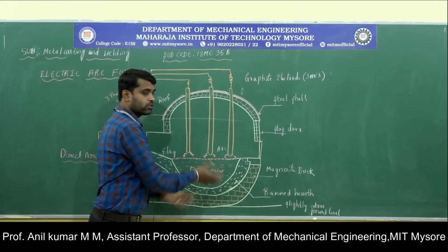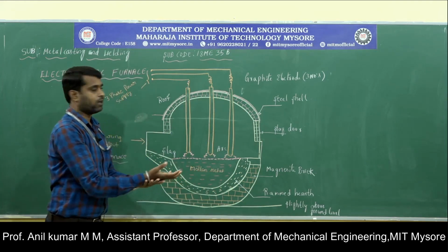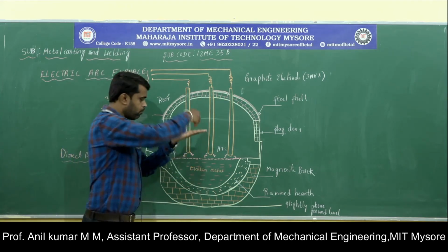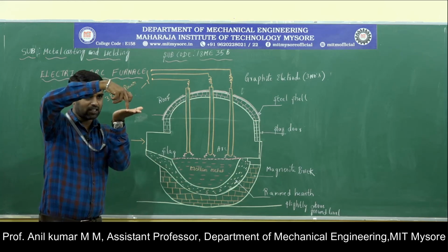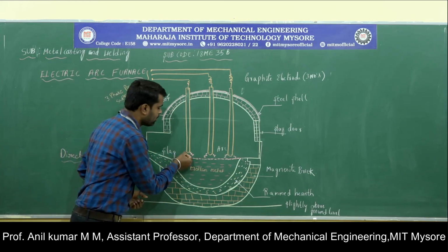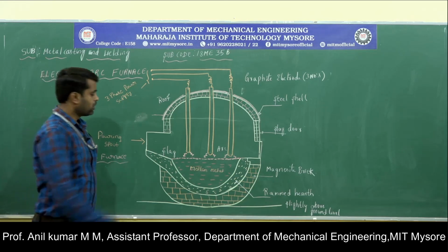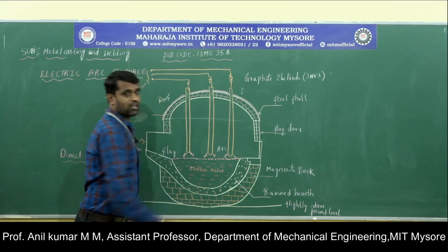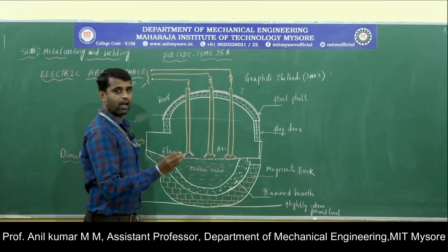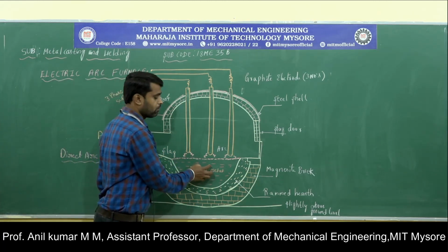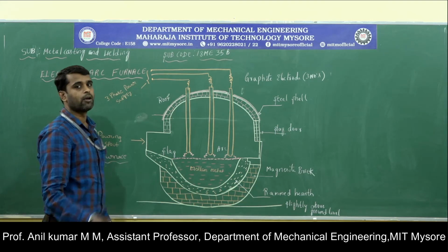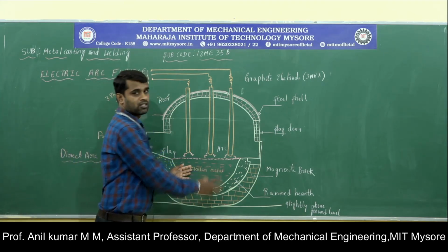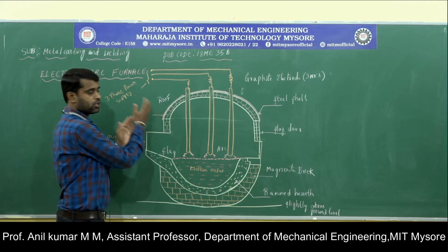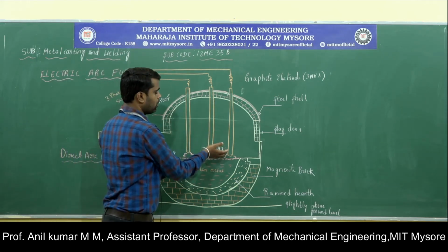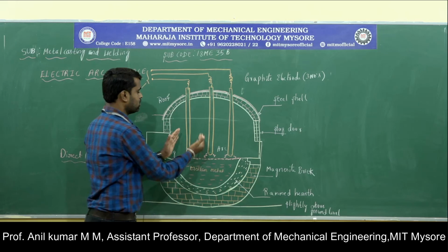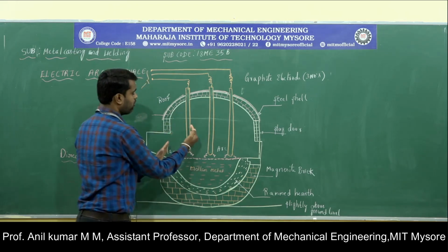Okay, these electrodes can be raised and lowered with the help of the guide. Initially you have to bring the electrodes closer to the metal charge and then separate them. At that time, in that gap the electric arc will be generated. This electric arc melts the charge inside the furnace because the temperature is very high. Due to the high temperature, whatever metal is placed inside the furnace will be melted. Once the desired temperature is reached, you have to cut off the power source, and then we can raise the electrodes out of the furnace.